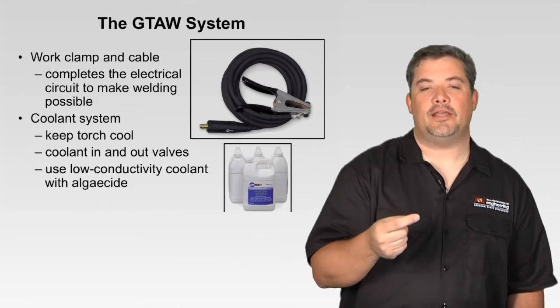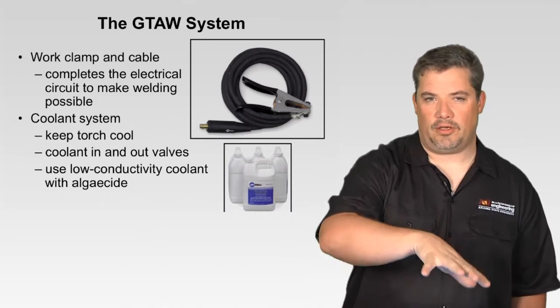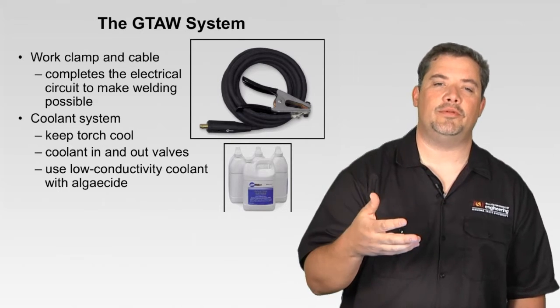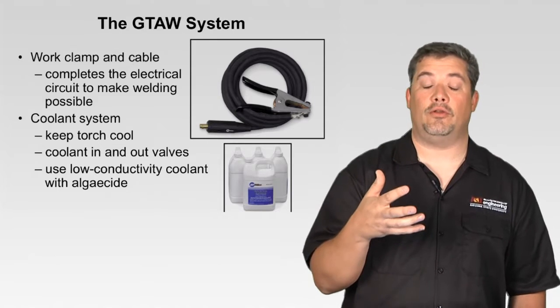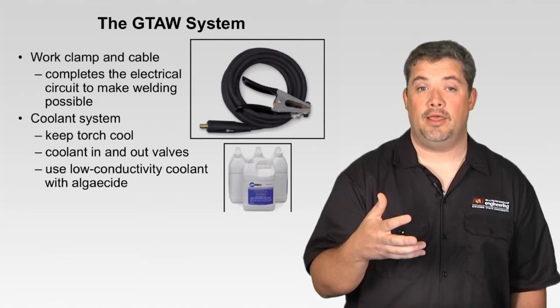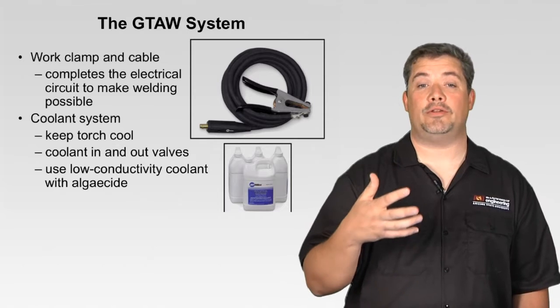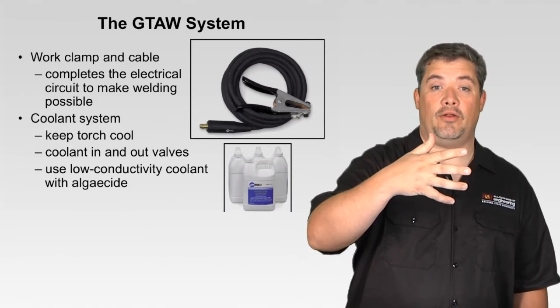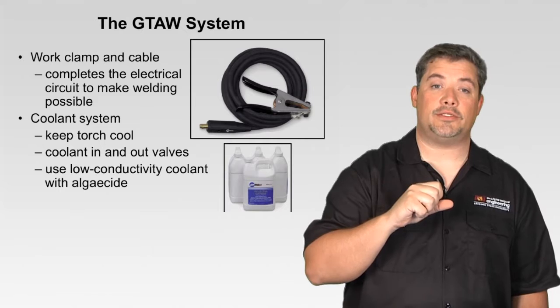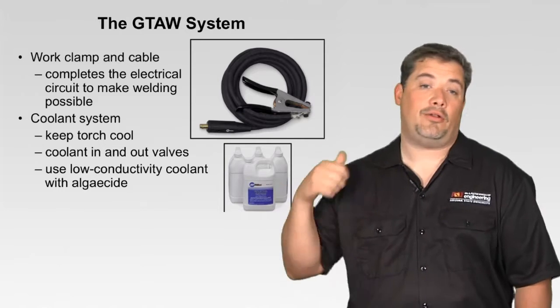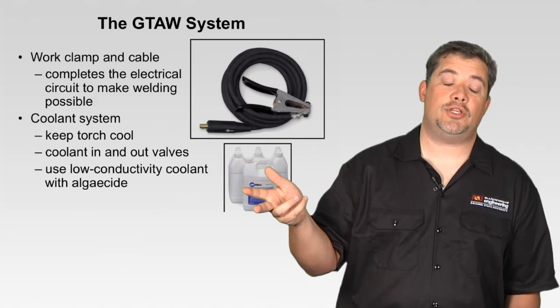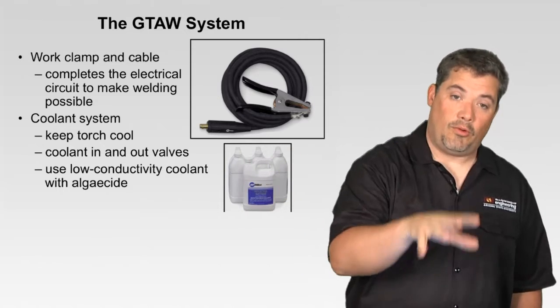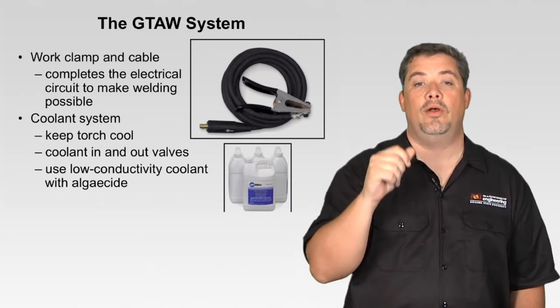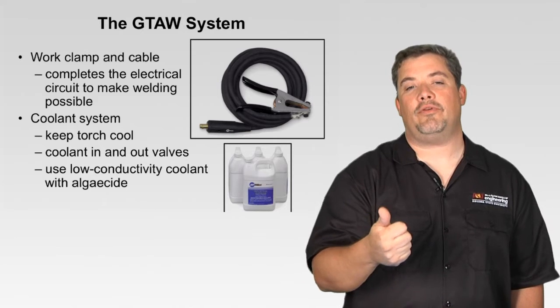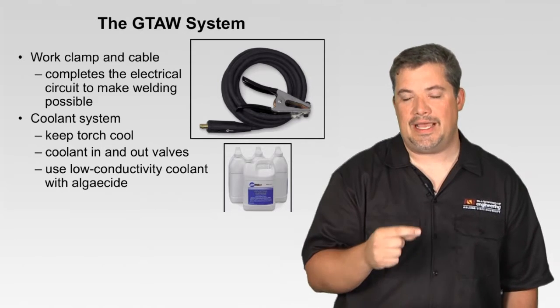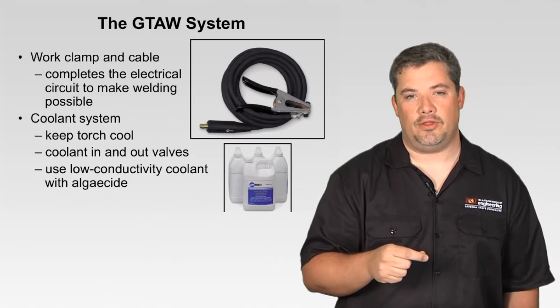The reason for deionized water is in TIG welding, and we're going to talk about arc starting methods, we use high frequency, and high frequency takes its path to earth ground however it wants to take. And if we're using just tap water, that is very conductive. So that high frequency, instead of jumping across the arc to start my arc for me, might travel down that water line and find earth ground through the case of the machine easier than where we want it to go to help me strike that arc. So low conductivity coolant by the manufacturer or distilled deionized water is all that you can use.